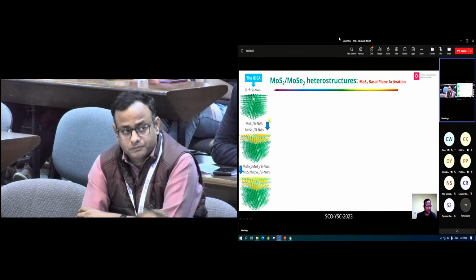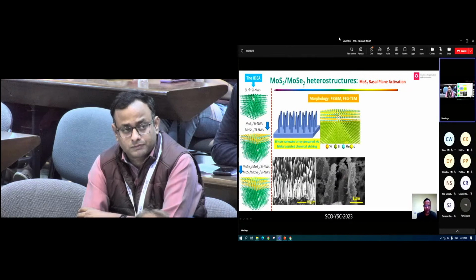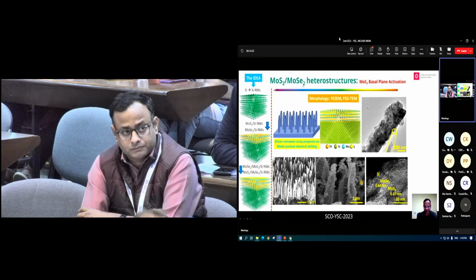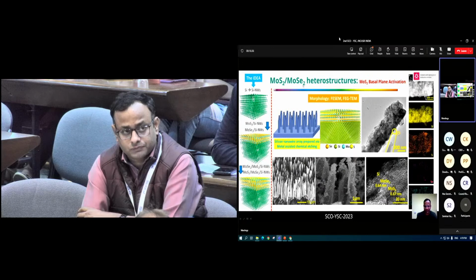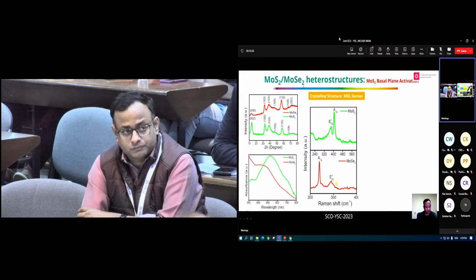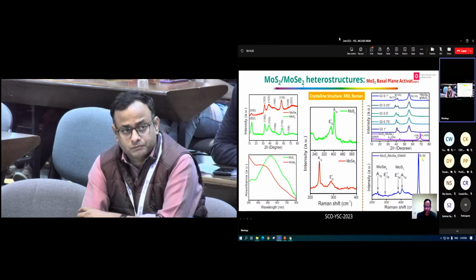What we have done is make heterostructures using MoS2 and MoSe2. In one experiment we have taken MoS2 on top, in the other experiment we have taken MoSe2 on top. First we addressed the materials science issue, so we have characterized them. We have taken silicon to silicon nanowire just to increase the surface area, the active area, and after characterization we could confirm the growth not only by morphology but also from the structural and optical properties. And you can see the complete device, with the silicon nanowire, MoS2 and MoSe2.